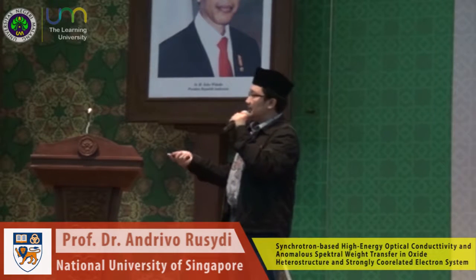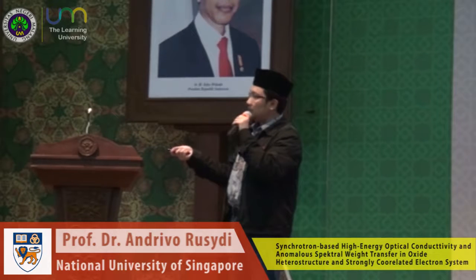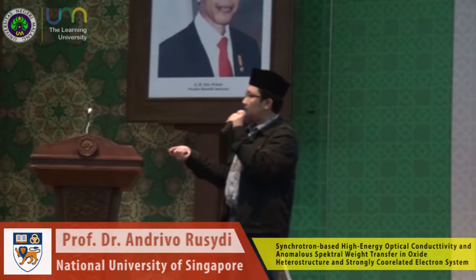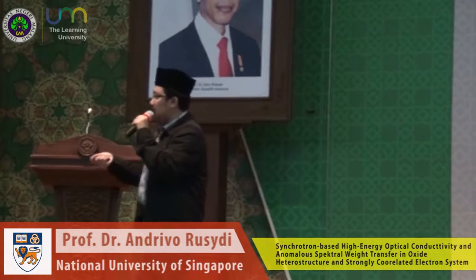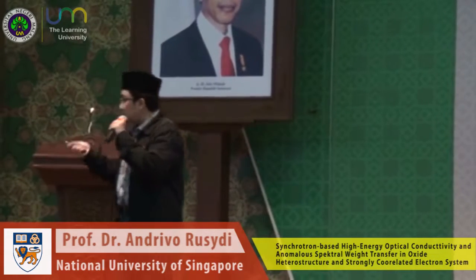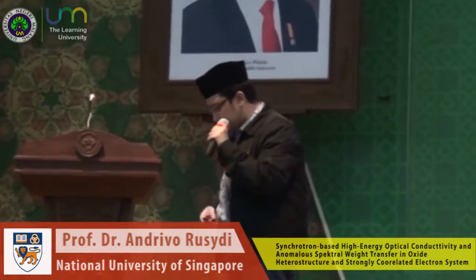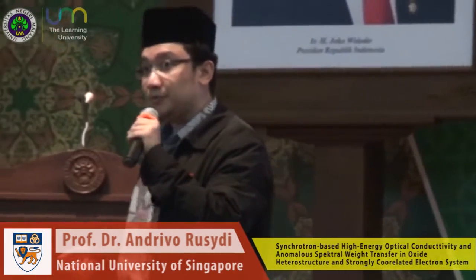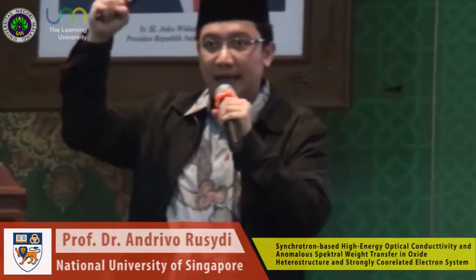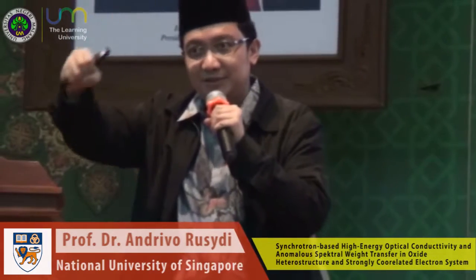What happened in the group by Harold Hwang, discovered around 2004, and Mannhart from Germany, and the Triscone group from Switzerland, is very fascinating. They grow layer by layer. They take strontium titanate, what we call the substrate, and put atoms on top of the SrTiO3. Then they grow what's called lanthanum aluminate, LaAlO3, and see what happens once you do that.